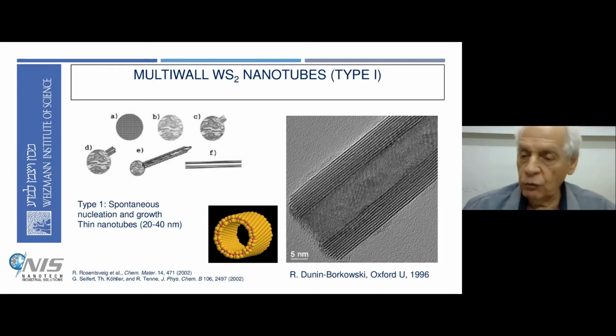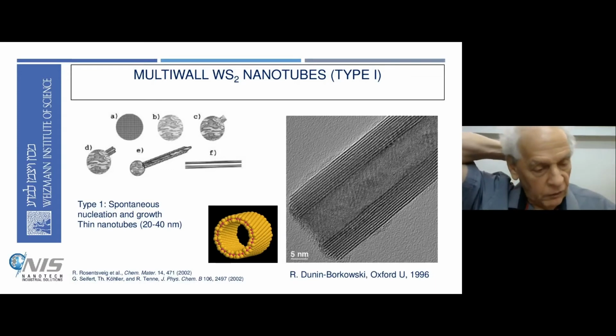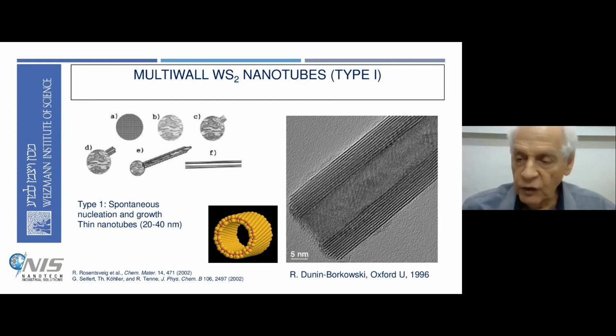You see how beautifully they are arranged, wrapped in layers one on top of each other. It's really a concentric tubular structure, and each fringe, each black line, is basically one layer of tungsten disulfide. You have about 10 layers or maybe more, growing bigger and bigger.